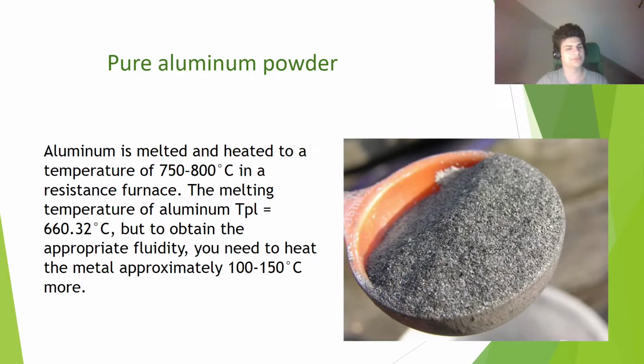Aluminium is melted and heated to a temperature of 750 to 800 degrees Celsius in a resistance furnace. The melting temperature of aluminium is 660.32 degrees Celsius. But to obtain the appropriate fluidity, you need to heat the metal approximately 100 or 150 degrees Celsius more.